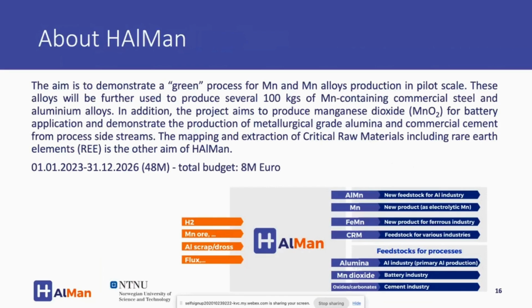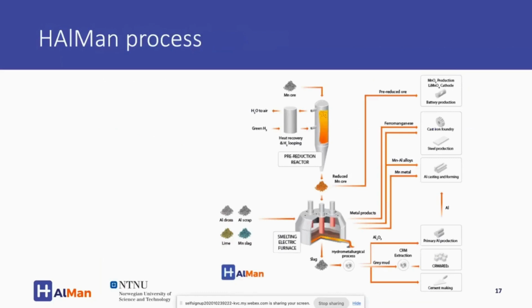So if you go to the next slide. And here you can see a more general simplified graph. So what we're doing, we first pre-reduce the ore in hydrogen, with 3 different technologies evaluated, which I will present later on. Then we take this pre-reduced ore and put it in a furnace where we do the aluminium reduction, the smelting. And this is done at Mintek in South Africa. Here we put in the aluminium dross and scrap as reductant. So the material coming in is Mn ore, already pre-reduced down to MnO.